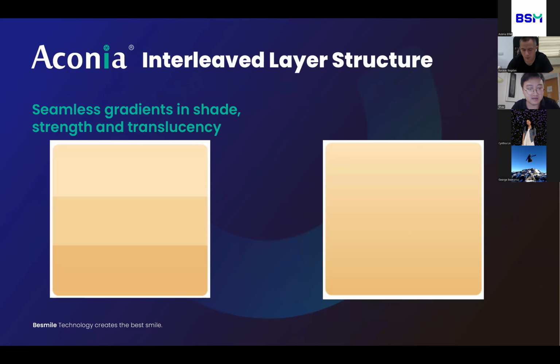Based on the traditional multilayer, we explored a new multilayer technology, the interleaved layer structure, on the 3D Master. With this spatial structure, 3D Master can achieve seamless gradients in shade, strength, and translucency. You can see that on the left side is a traditional multilayer. In the traditional multilayer, there are some obvious boundaries between the layers, but on the right side, in the 3D Master interleaved layers, the transition is smooth.